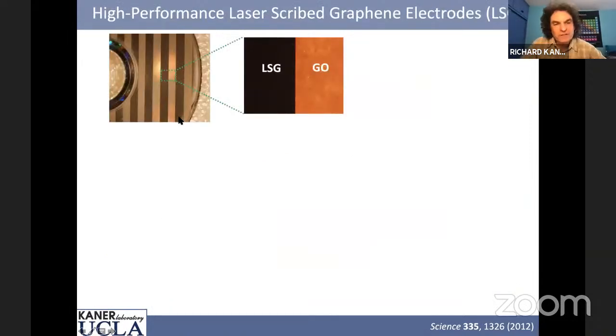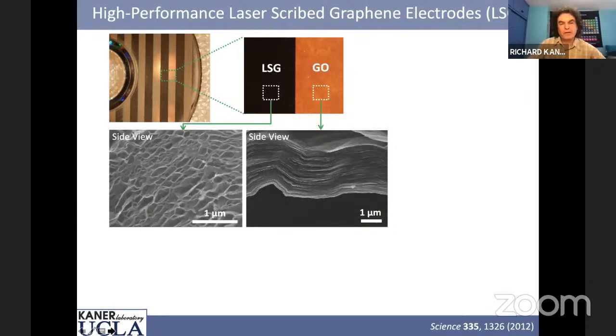Now, this is an interesting experiment. We told our laser to draw stripes on our disk. And so where it's converted, this is laser scribe graphene, and where it's not is just graphite oxide. And if we look under a microscope, you get a good idea of what this material looks like. So graphite oxide is this beautiful layered material. You can see it here. When we hit it with the laser, it absorbs light, it gets hot, and it blows off CO2. And what's left is a fractal.